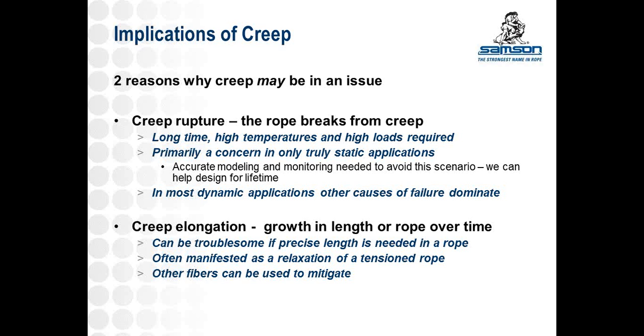As I said, it's really a concern in these static applications where there's an installation put in place that is going to remain under load for large periods of time, or it's at a high temperature. If there is any scenario like that you encounter with a customer or potential customer, and you need some advice as to what is the expected lifetime or the creep lifetime, we can certainly do those calculations, and you can get in touch with us, and working together with DSM Dyneema, we can get a pretty accurate model along with uncertainties and tolerances in terms of how long you can expect that rope to last under a certain load.